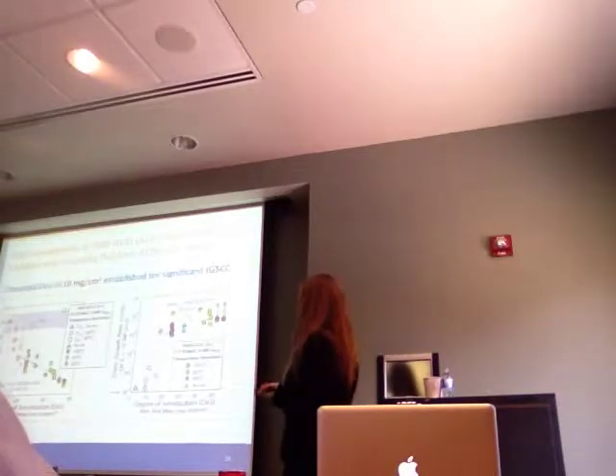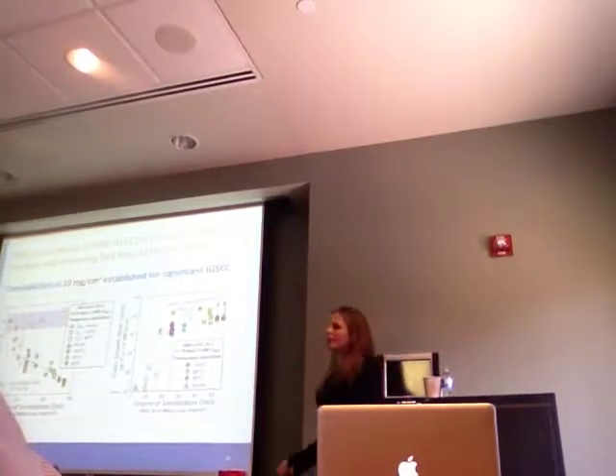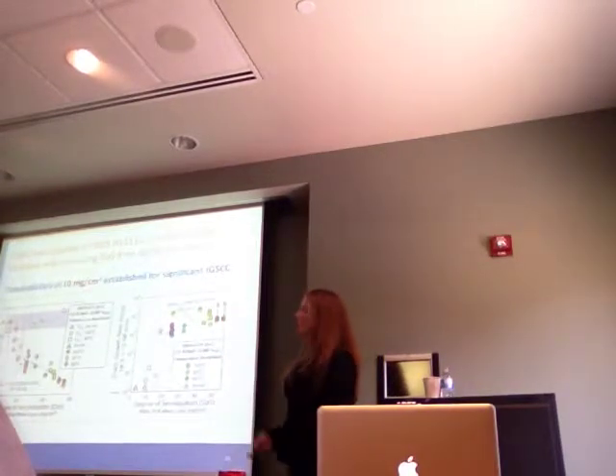And the same thing can be seen for the crack growth rate. At low crack growth, or at low degree of sensitization, your crack growth is very low. This arrow represents your resolution limit. As you increase the degree of sensitization, your crack growth takes off, and then it levels out, but continues to increase with further sensitization. So this DOS level is very important for stress corrosion cracking in this alloy, in this environment, NaCl at -0.8 volts.